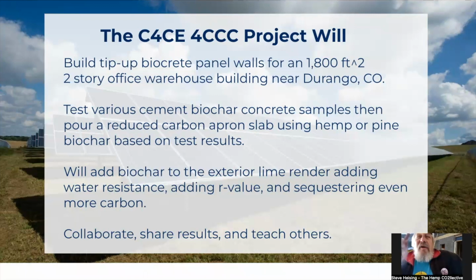We had biochar. Biochar is the carbon in the hemp plant that if we pyrolyze it, which means cook it without oxygen, we can drive off the syngas, we can drive off the liquid bio oils, and we end up with carbon at the end that transformed itself from long chains of cellulose and hemicellulose into more graphene and graphitic type ring structures, which are very strong. We know from the literature that if we put graphene in concrete, it makes it 30% stronger. If it makes it stronger, we could use less of it, I think.